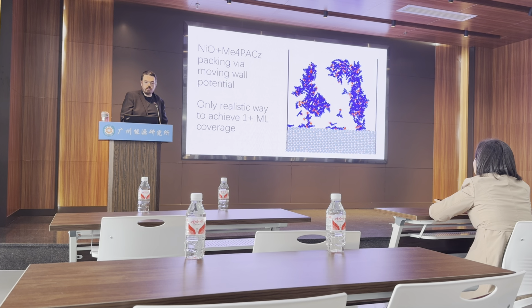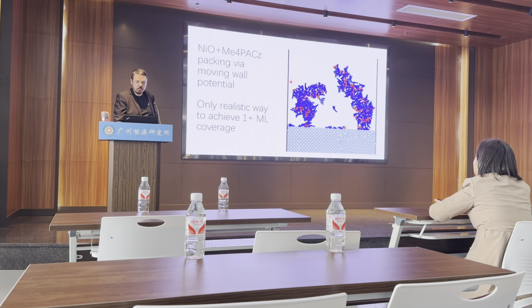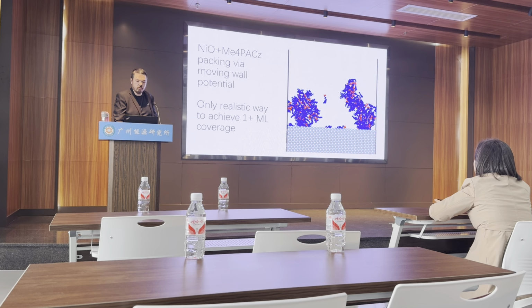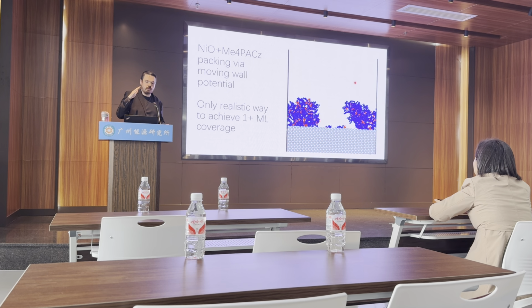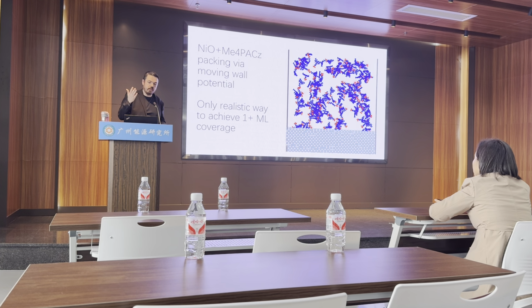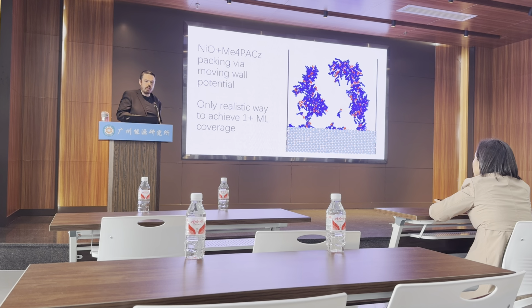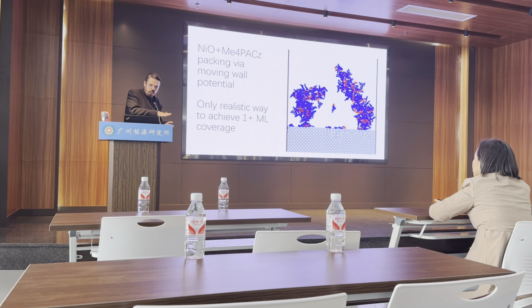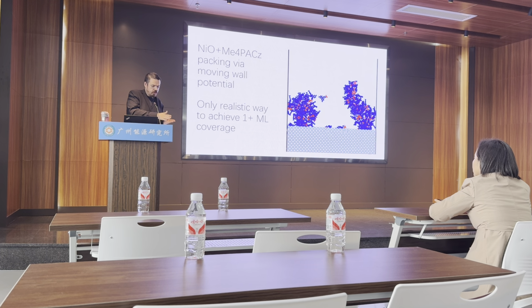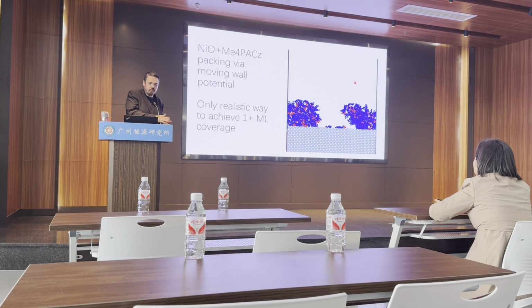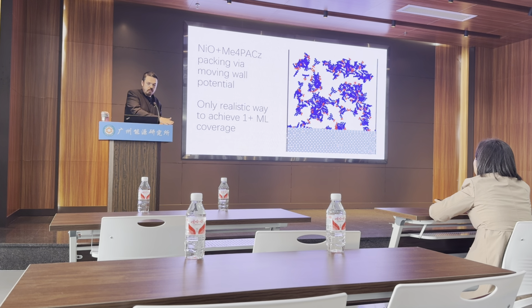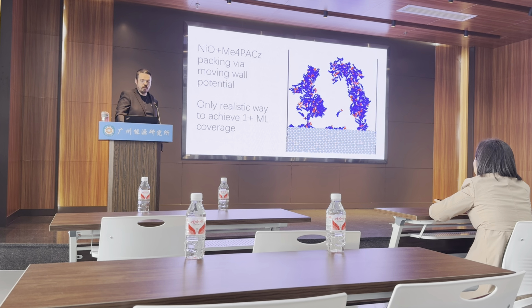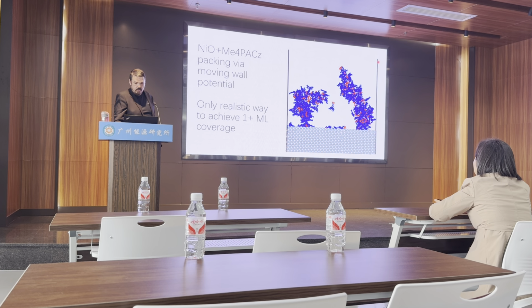Anyways, once that was all done, basically we populate this space above with our SAM, and then we actually have an application process, just like an experiment, right? It's you press down with the perovskite, so we press down a wall on the SAM, and that way we get a realistic case where the SAM actually formed the film, like in real life.